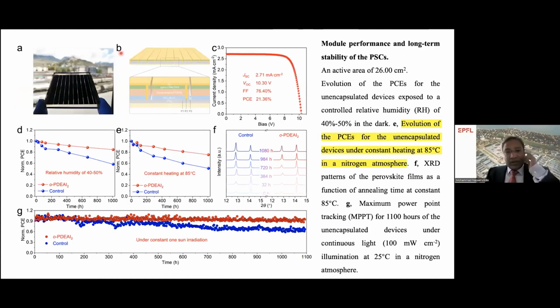a contact. And we also made small mini modules, and using this type of configuration, you can see the beauty here at 40 to 50% humidity. The reference sample is decreasing significantly compared to the ortho-substituted cation-containing perovskite solar cells. At the same time, we test stability at 85 degrees temperature. The reference sample is decreasing significantly compared to the ortho-substituted ones. But if you look at the unencapsulated cells under argon or nitrogen atmosphere at 25 degrees under full sun, the efficiency remained intact over 1000 hours compared to the reference sample.